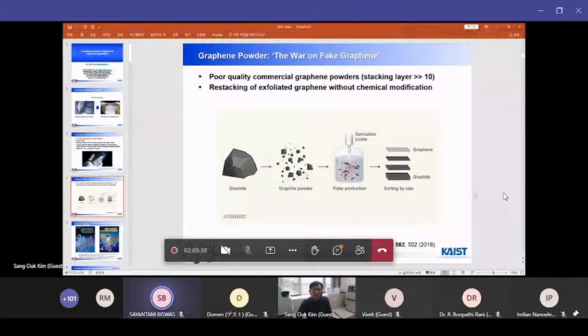And actually, the reason is that the most popular graphene production method is a simple physical process, applying a very strong shear field. But this simple physical method can only temporarily exfoliate graphene, and without any chemical modification, it wants to go back to the initial original stacked structure. That's the problem, right? Restacking of temporarily exfoliated graphene is the fundamental and unavoidable issue for physically obtained exfoliated graphene. That's why it's really hard to find a powder sample which can really be defined as graphene nowadays.